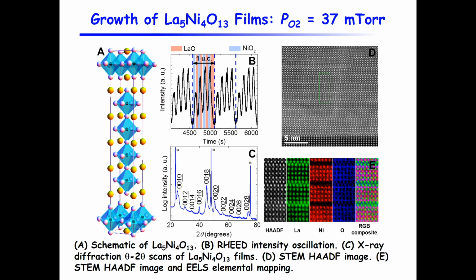growth. And here, actually, we shaded the intensity oscillation. So you can see that for every 4 1-to-1 depositions, for this time for lanthanum oxide, we just extended for some more laser pulses to add another lanthanum oxide layer. So we were able to grow the right phase, and the TEM shows that indeed every 4 layers we add one more lanthanum oxide layer.